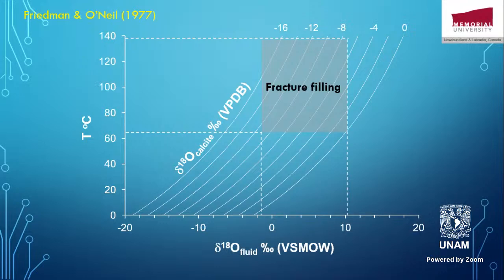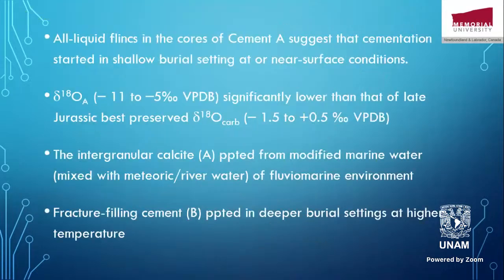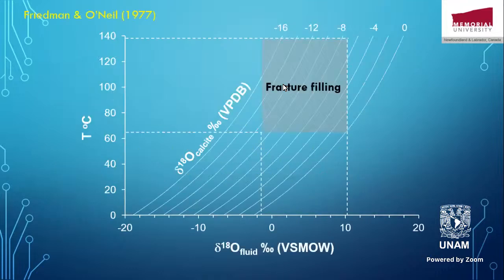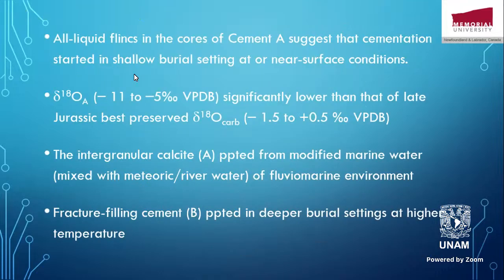So at lower temperature, the oxygen 18 goes to the heavier phase, which is the cement, the diagenetic phase. But when the temperature goes up, the oxygen 18 stays in the light phase, which is the liquid. It doesn't go to the cement. So, with the all-liquid inclusions in cement A here, we suggest that cementation started, as I said a moment ago, in a shallow burial setting. And the delta O18 of that cement A was between minus 11 and minus 5, significantly lower than that of the late Jurassic preserved carbonates, between minus 1.5 and plus 0.5.